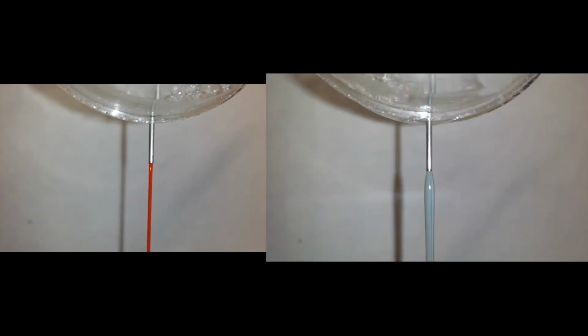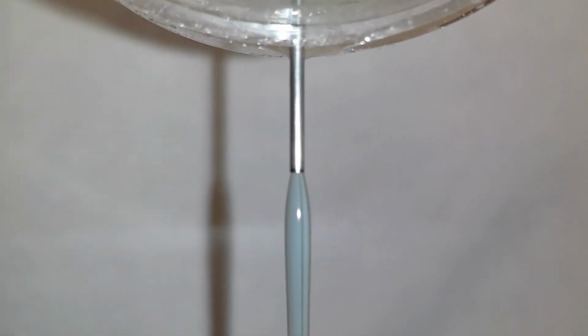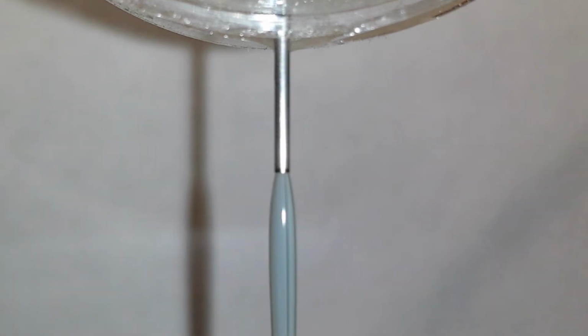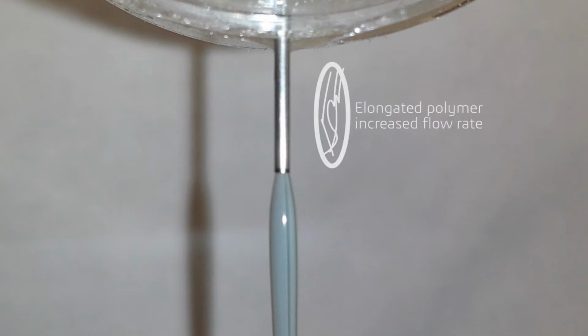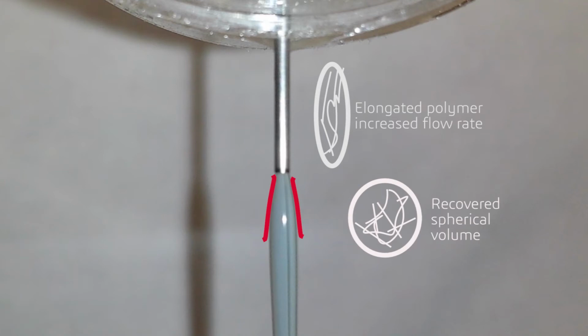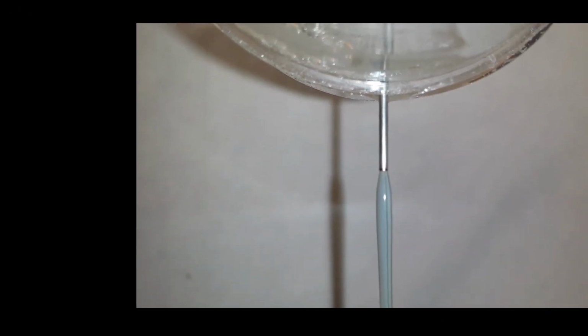The polymer stream is compressed when entering the small tube, and will swell back to its former shape and volume after exiting the orifice. This is a phenomenon directly related with the entropy and relaxation time of the polymer. Initially, a flow stream has a constant rate before entering the orifice, and the polymers within the stream occupy a roughly spherical conformation, maximizing entropy. Inside the tube, the polymer loses its spherical shape, becoming longer due to an increased flow rate. When the polymer stream leaves the orifice, the remaining physical entanglements cause the polymer stream to regain a portion of its former shape and spherical volume, in order to return to the roughly spherical conformation that maximizes entropy.